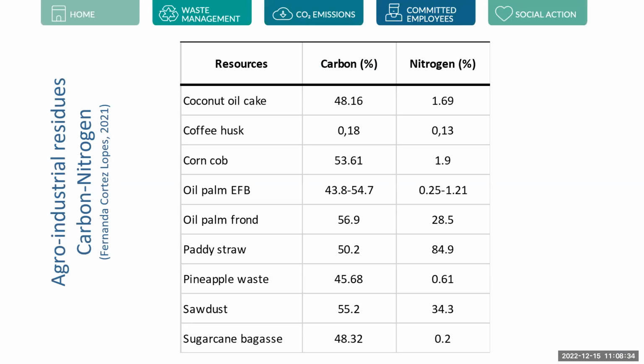Okay. As I mentioned previously, bacterial cellulose could be produced in a suitable medium containing carbon and/or nitrogen. And then how could agro-industrial residues play a role in bacterial cellulose production? This slide shows the carbon and nitrogen content in several agro-industrial residues, and depending on the type of plant, the concentration of carbon and nitrogen varies. This content, of course, will affect the bacterial cellulose properties such as mechanical strength and crystallinity, which further affect the performance. It has been proved that the higher the content of carbon and nitrogen, the higher the mechanical strength of the bacterial cellulose produced.